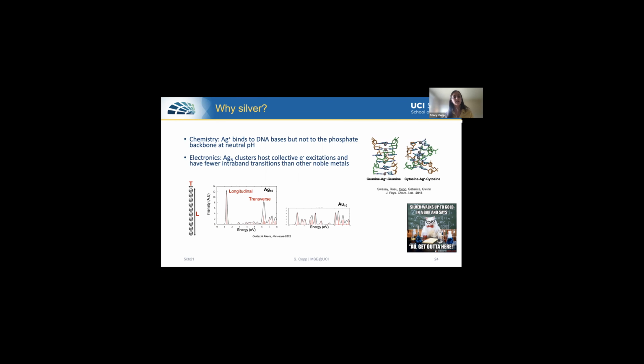Another reason is electronic or physics-based. And that is that silver clusters are able to host what are called collective electronic excitations, meaning the electrons in the cluster will be moving together, so sloshing back and forth longitudinally along this rod or in a transverse direction. And as compared to something like gold, we can get these really strong intensity peaks in the excitation spectrum, meaning that all of the electrons are involved in the process. So it's a much more intense process. The reason why we don't see this in gold or other types of metals is because the electrons prefer to, in a singular fashion, hop between energy orbitals and not move collectively.